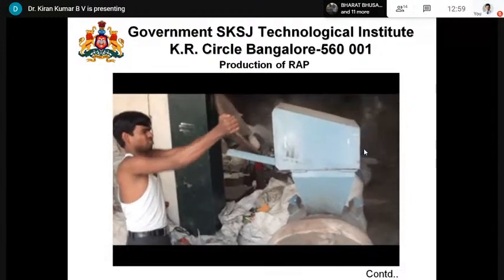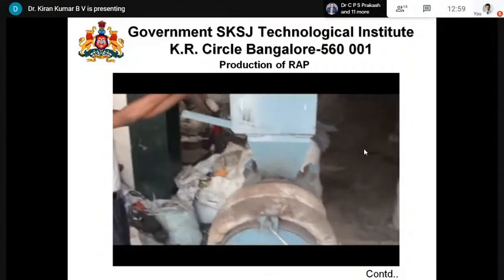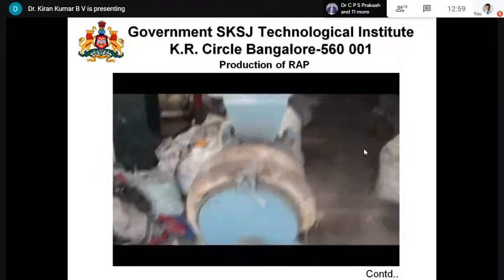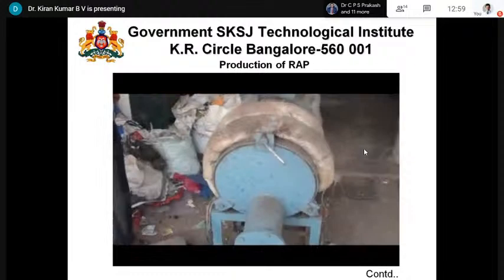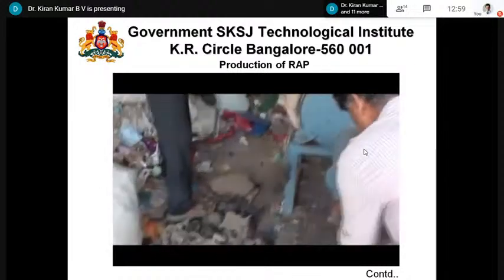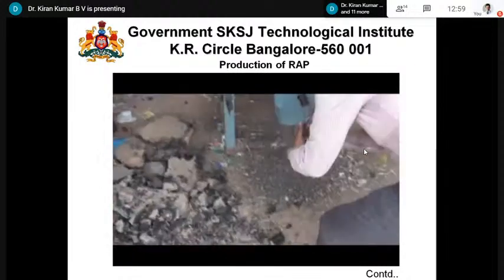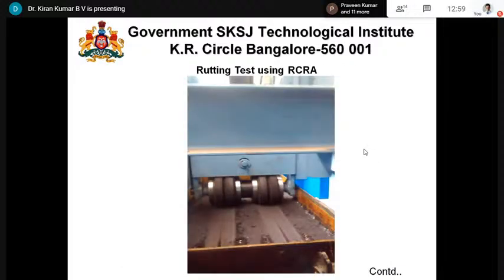We have removed that road by shallow cutting and depth, brought them in bags and placed them in our site, and we did this because this was a small test track that we wanted. This is the condition or the shape of that particular material, heated, and then we brought this and removed that in our processing site, and then we collected this aggregate and transported it to the hot mix plant for further evaluation. So this is the site.